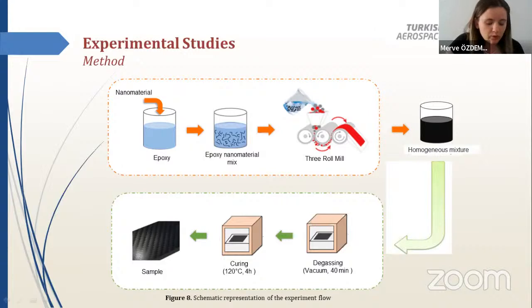Then carbon nanofiber increases the viscosity of the resin. Carbon nanofiber concentrations were 0.1, 0.5, 1, and 2% by weight. Secondly, the resulting resin and nanomaterial mixture was processed using the three-roll mill, and hardener was added to the homogeneous mixture. Then the mixture was degassed under vacuum. Finally, the mixture was cured at 120 degrees centigrade for 4 hours, and samples were produced.